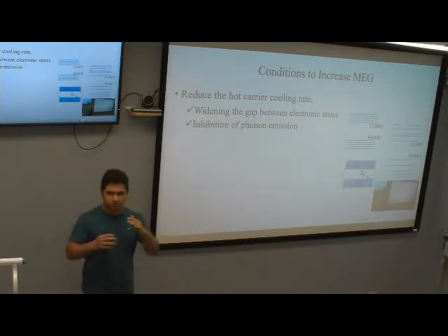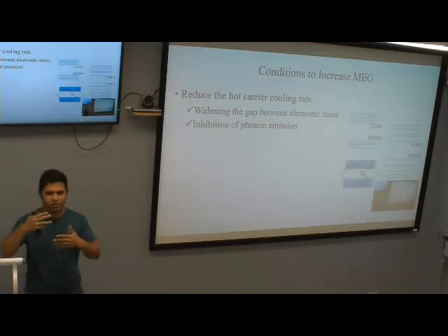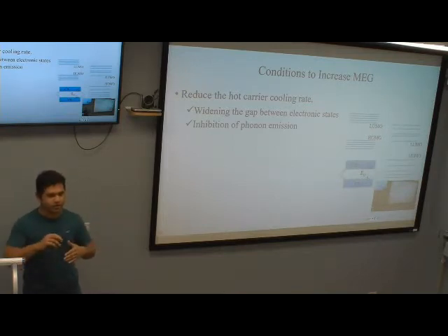We know that in bulk material, all states are very dense, almost continuous. Due to that, hot electrons can relax by dissipating the energy through phonons, because the energy differences are very small, so they have a higher probability to couple with the different phonon modes.